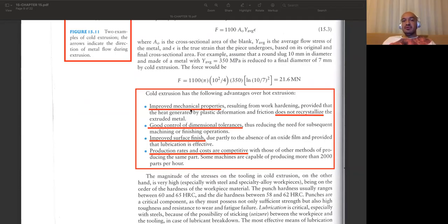Another thing, we have improved mechanical properties like the strength, since we have work hardening and the size of the grains is decreased. But the thing is that you should be careful about friction. If you have too much friction, then this may increase the temperature of your workpiece, and if it is increased, then you may start recrystallization. If that is the case, then it will be a kind of hot extrusion process.